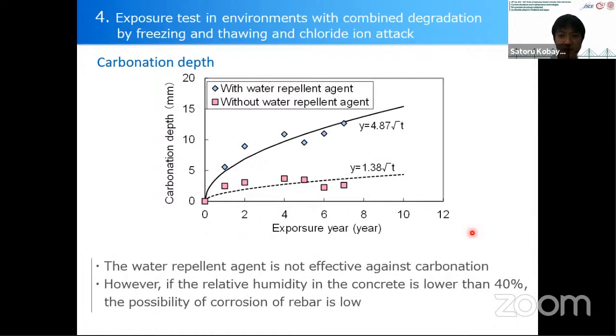And this is the result of carbonation depth. It's the same result as the exposure test under chloride attack environment. The water repellent agent is not effective against carbonation like this. The carbonation depth is bigger than without water repellent agent. However, it is said that if the humidity in the concrete is lower than 40%, the possibility of the corrosion of rebar is low. So I'd like to check the carbonation of existing concrete structures, which used a water repellent agent, in the near future.